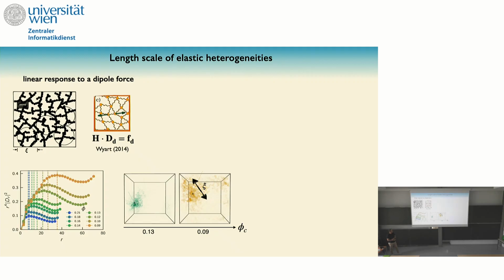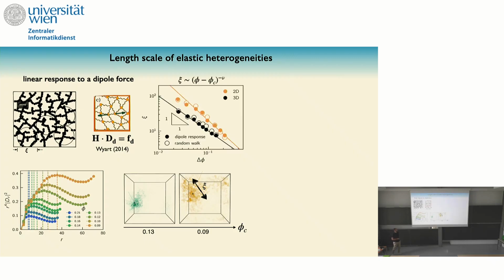So this is a picture that shows you the size of these blobs, of these heterogeneities. If you are far away from the critical point, or the rigidity percolation point, so if the system is dense, you see that this length scale is small. And when you get closer, this length scale gets bigger and bigger, which means that your system is getting more and more heterogeneous. So you can extract this length scale as a function of the distance to these critical points. And in 2D and 3D, it follows the expectation that you get from the correlation lengths with the exponent that you have measured before. So in 3D, it was 1, and in 2D, it was 1.3.